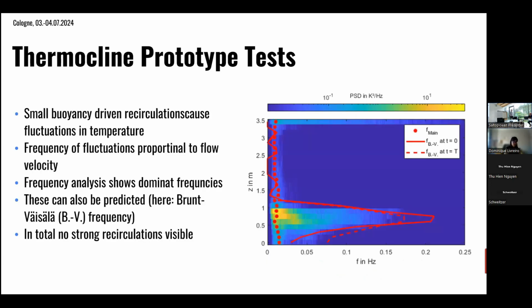And then in a collaboration with the TU Ilmenau, there was a PhD candidate looking deeper into the topic. What he was investigating was small recirculations happening in near wall regions. If these small recirculations are happening here, you would see some fluctuations in the temperatures. So you can measure temperatures anywhere, and if there's flow, you would have some fluctuations in the temperature. These temperature fluctuations have a certain frequency, and by a frequency analysis, you can identify salient frequencies.